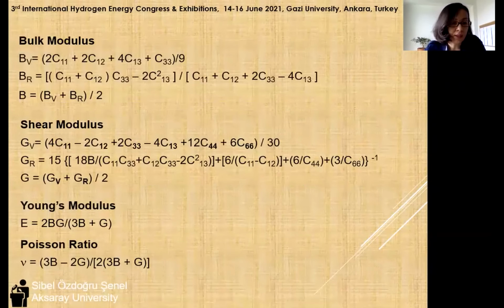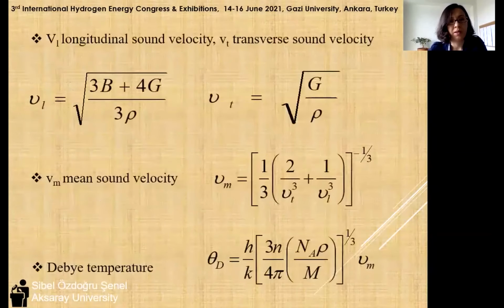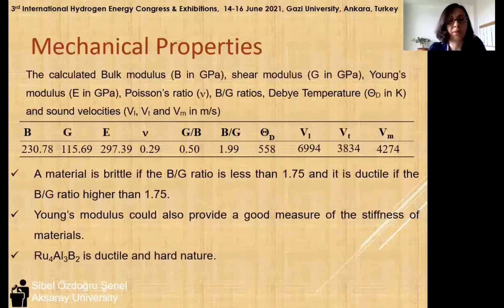Polycrystalline elastic moduli are calculated using the Voigt-Reuss-Hill approximation. The equations are given here. In addition, ambient sound velocities and the corresponding Debye temperature were calculated with the equations given here. The calculated bulk modulus, shear modulus, their ratio, Poisson's ratio, Debye temperature, and sound velocities are given in the table.